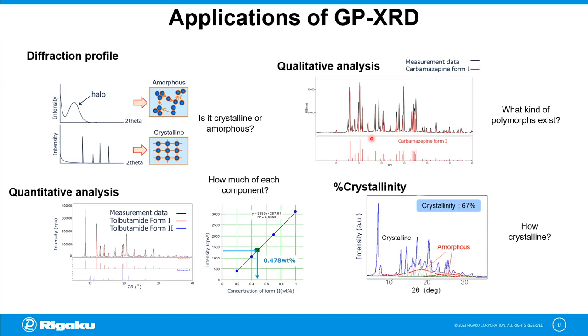Then we can determine percent crystallinity, how much of the material is actually crystalline versus how much is amorphous. Again, back to this halo here. We can also do quantitative analysis, and that means determining what percentage of each component is in there. All these are extractable from the powder diffraction data.